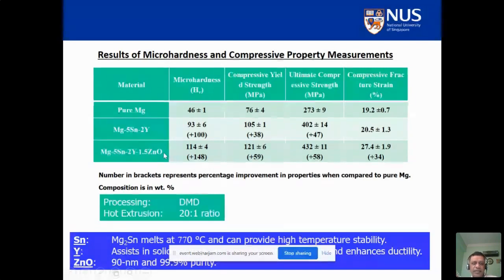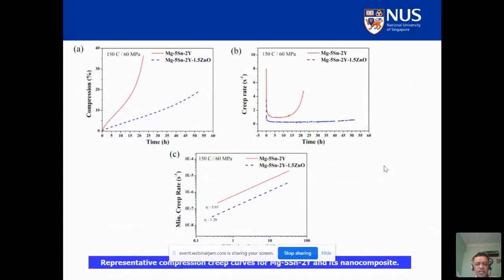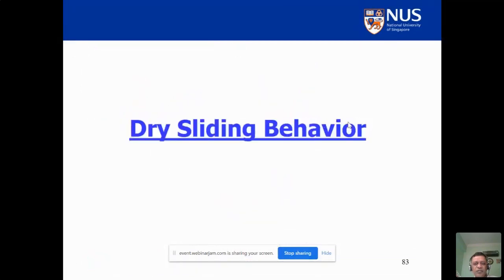And then we add zinc oxide. Again, we are able to increase hardness by up to 148%, yield strength by 59%, and ultimate compressive strength by 58%. And ductility jumps by 34% to 27.4%. With 27.4% ductility, you can manufacture very intricate shapes. After these properties, we sent it for the creep response. And the blue curve shows that the creep resistance increases for these materials and is much better than the unreinforced materials. So the presence of nano reinforcement also helps in enhancing creep response.